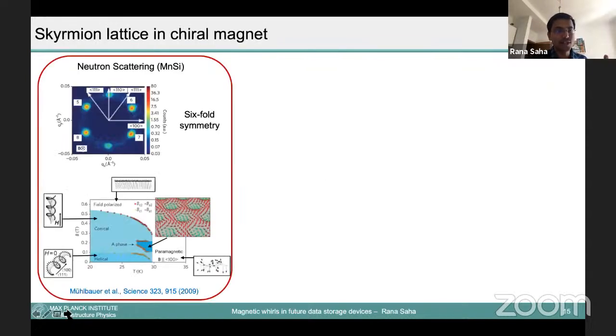So this is the first example of this structure, which was discovered by a German group in Munich by neutron scattering. You can see the structure has a six-fold symmetry, which indicates this is a skyrmion phase. You start from the helical phase, as I told you, and then you apply a magnetic field. It goes to a skyrmion structure, and if you further apply a magnetic field, it goes to a conical structure and then to a ferromagnetic structure.